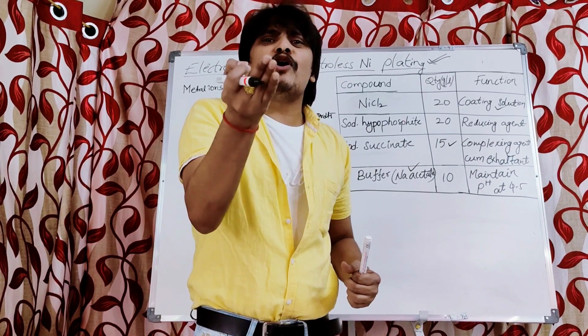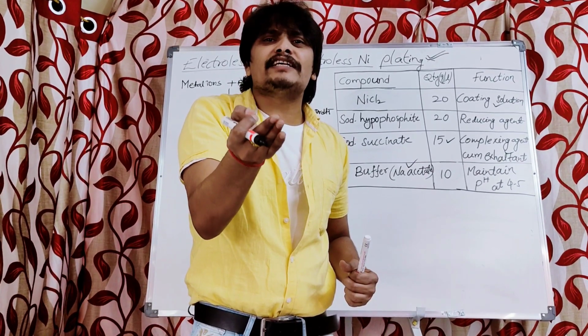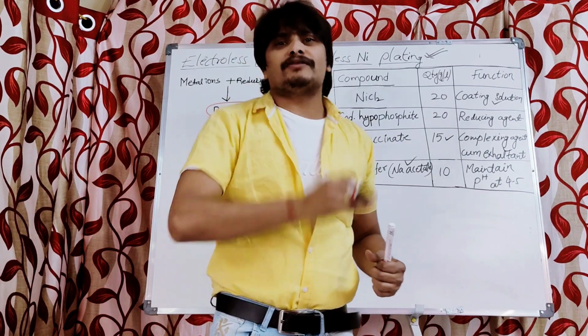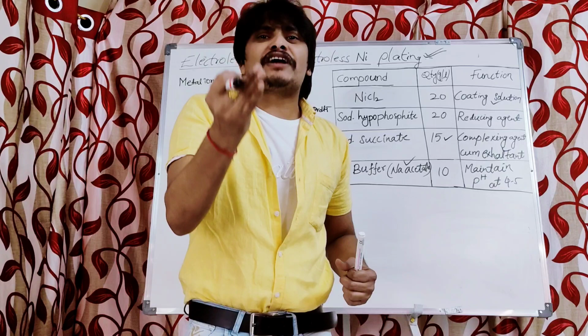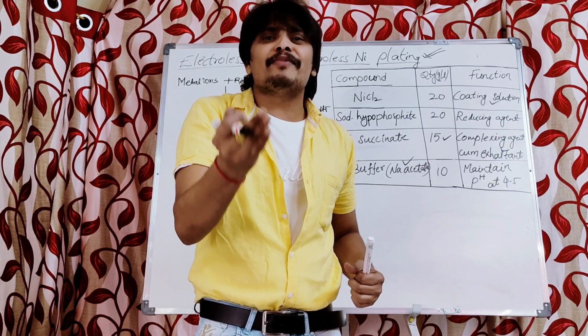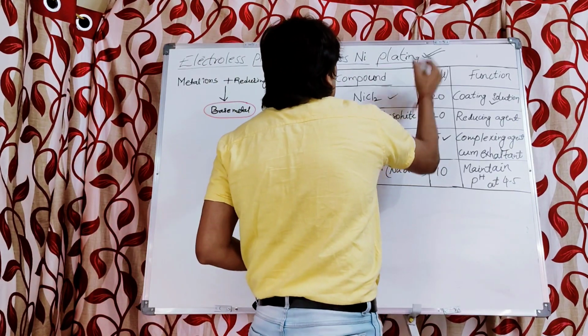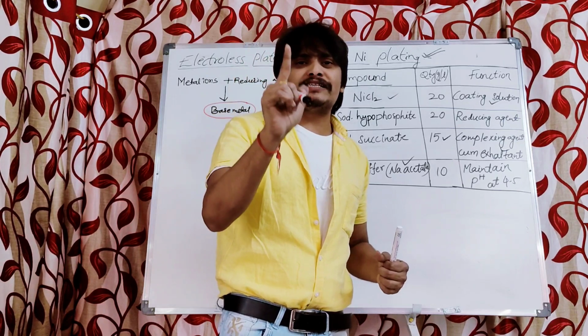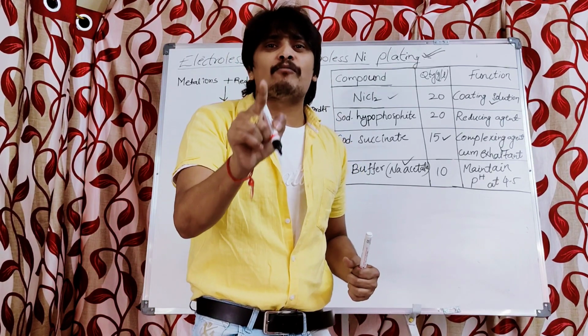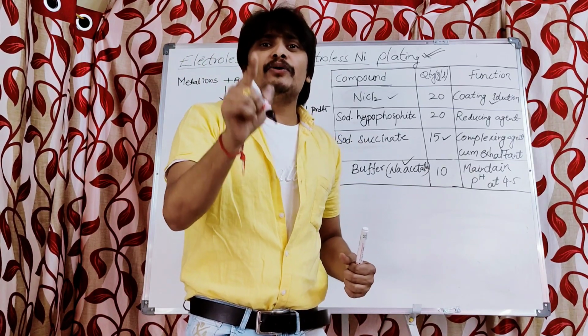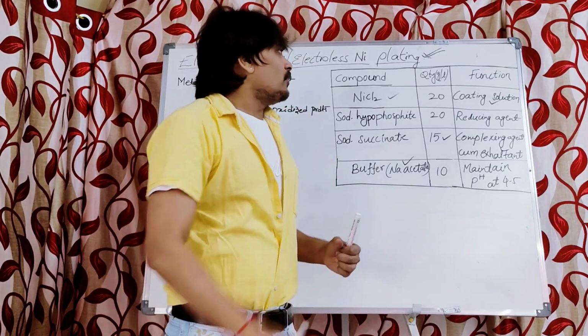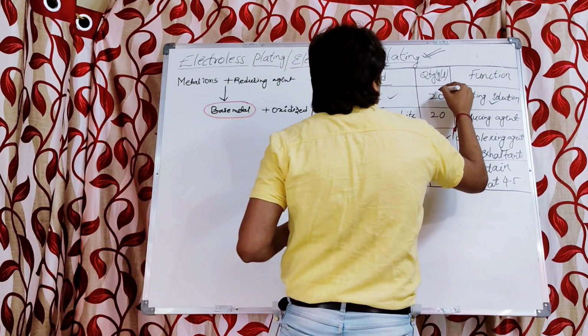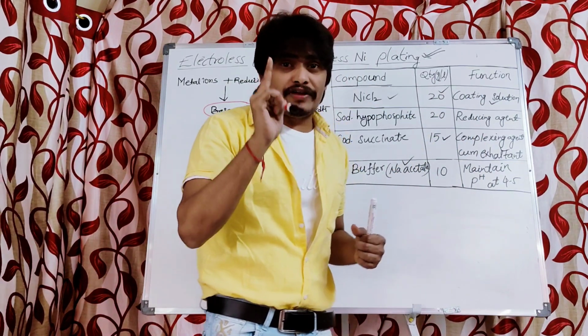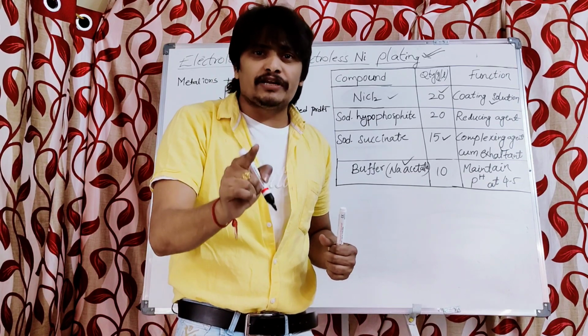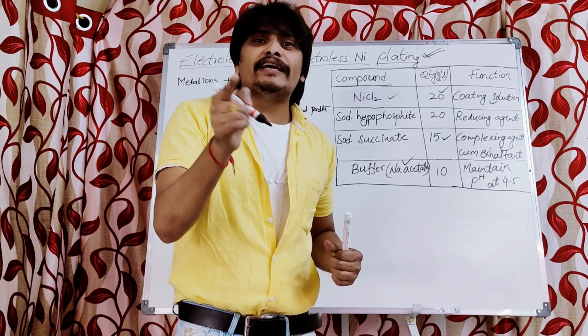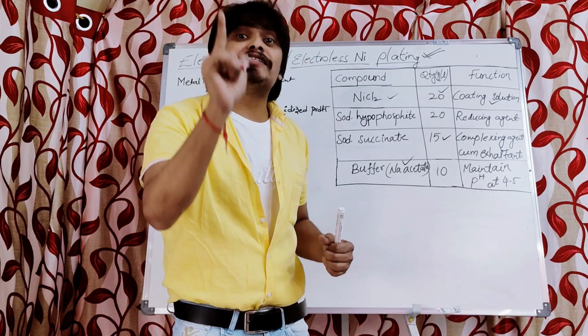Since it is a noble metal, we have to take the salt in such a manner that it comprises the nickel metal ions. What is that salt? It is nothing but nickel chloride salt. Already I have discussed that we have to consider the calculated amount of each ingredient during the preparation of the composition bath. The quantity of nickel chloride to be taken is 20 gram per liter. So we prepare the nickel chloride solution by dissolving 20 grams of nickel chloride in 1 liter of distilled water.